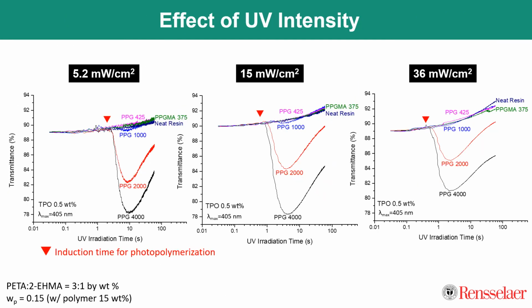So now moving forward, that same plot that I just showed is on the left right here, and the next two are the same sort of plot but at a higher UV intensity, and we can see the same trends are visible. However, there's something else that we can notice here. As you go from left to right, or as you increase that UV intensity, the extent of how far this dip in transmittance goes decreases. So essentially, the extent of phase separation is decreasing with an increased UV intensity.